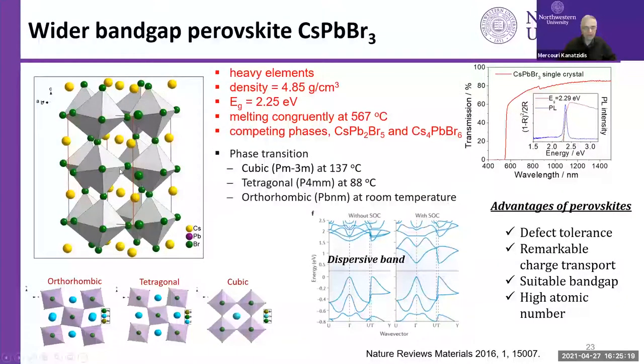So this is the structure. The perovskite has octahedral lead atoms surrounded by an octahedron of bromine atoms. Basically, the octahedra then share corners to make a three-dimensional structure. And then in the cages that form, you have the cesium atom. So it's a simple structure, but it's also complicated in the sense that these octahedra are dynamic and they can rotate back and forth, giving rise to phase transitions like you see here.